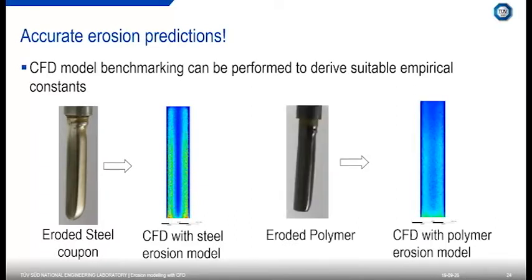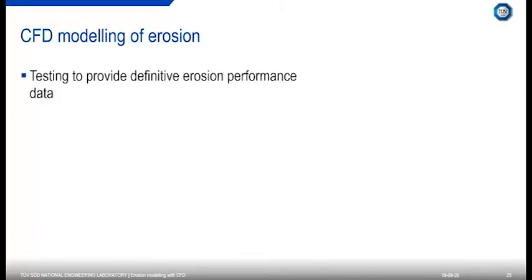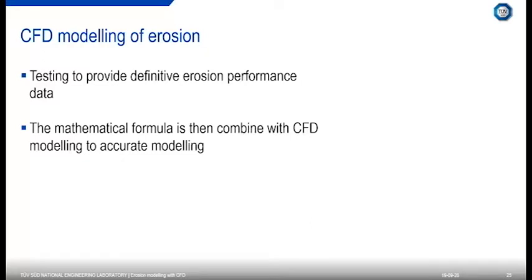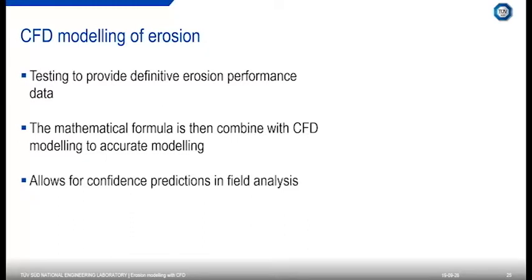If we have a polymer or a composite or a different material, then yes, we'll need to spend a bit of time and actually develop a model. But once we have this model, we can then apply it to field conditions or more realistic applications other than a coupon. So in CFD modeling of erosion, the testing is used to provide definitive erosion performance data. And we use this mathematical model combined with the CFD to give us an accurate model, and it allows for confident predictions in the field analysis.